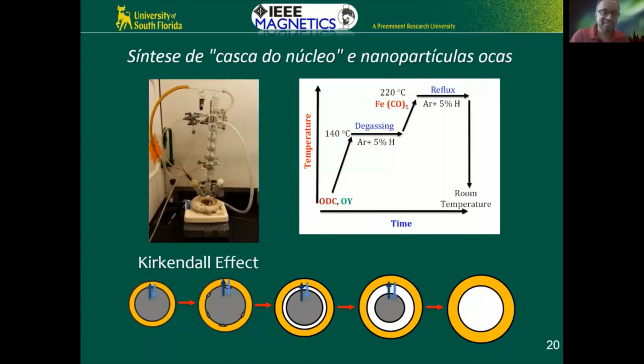Okay, so it turns out that if you think of the metal core, the iron core, and the iron oxide shell, there's a problem because of the differential diffusion of the metal ion versus the oxygen ion. Because of this, there are instabilities at the interface, which cause these holes, the voids, to open up. These holes get bigger and bigger, and finally the iron inside oxidizes, leaving it completely hollow inside, and the iron oxide shell gets thicker, so you get beautiful hollow nanoparticles.